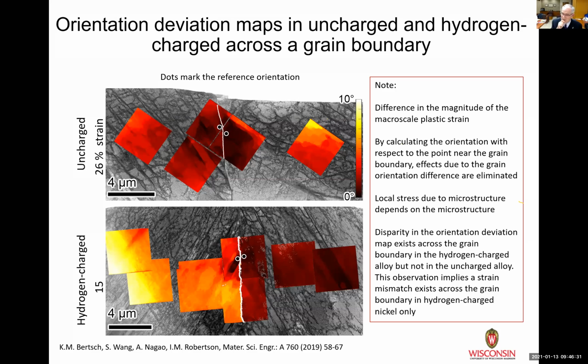What does that tell you? Well, if we think about deformation of a polycrystalline material, you have to get communication of strain across the grain boundary. The reason the boundaries stay intact is that you can communicate that strain across the grain boundary. It's not always done by the transfer of dislocations, but what's happening on one side of the boundary influences what's happening on the other. If it's a good, strong boundary, it will communicate the strain from one side to the other very well. If that's true, there should be no mismatch in the misorientation difference as you go across. And you'll notice there is no real difference here, at least in the upper image.